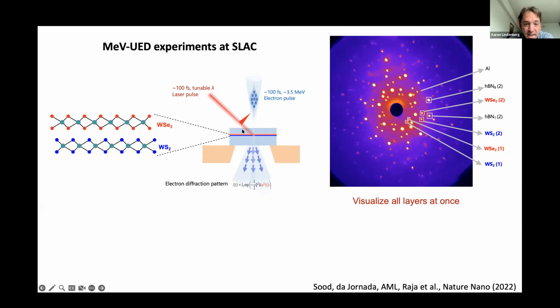It's actually encapsulated inside hexagonal boron nitride, and then it's freely suspended on a support structure. So we can do transmission mode electron diffraction experiments, probing the structure under optical excitation. Here on the right is a measurement of the diffraction pattern. It's a really amazing diffraction pattern, I think.